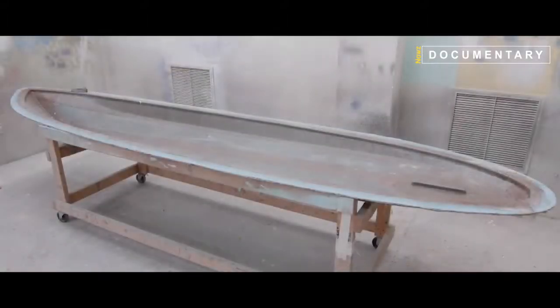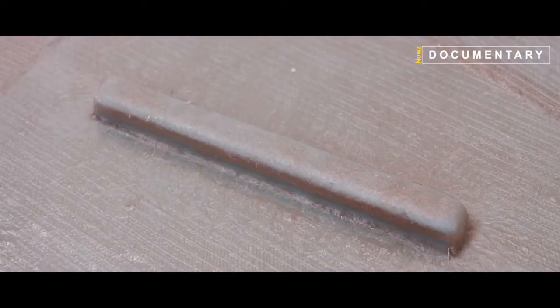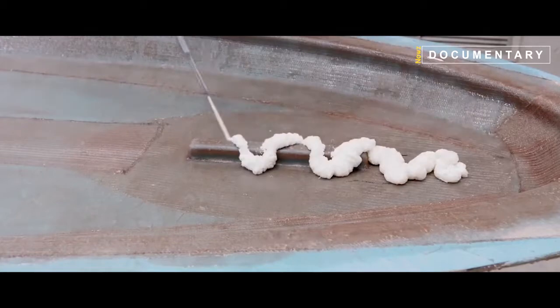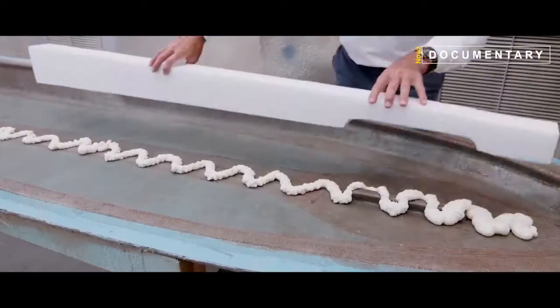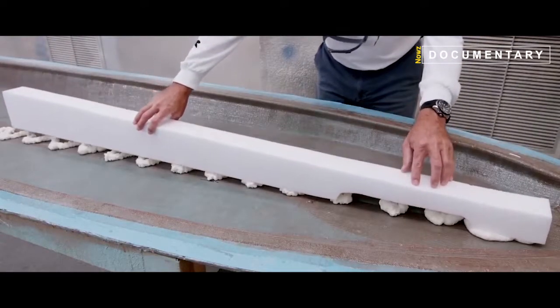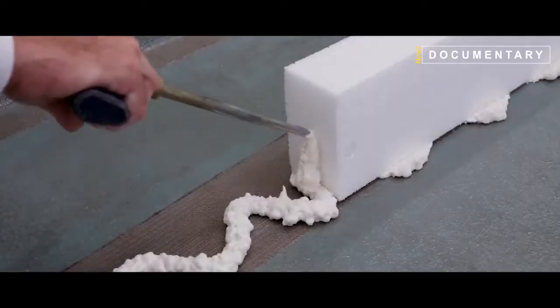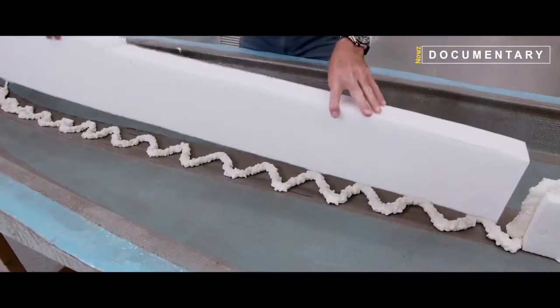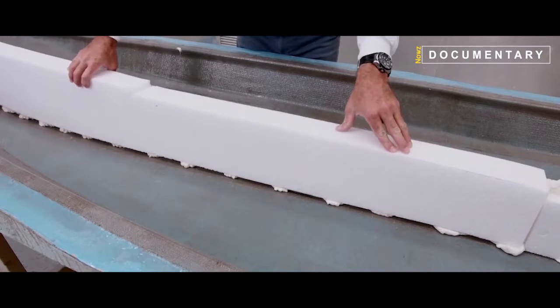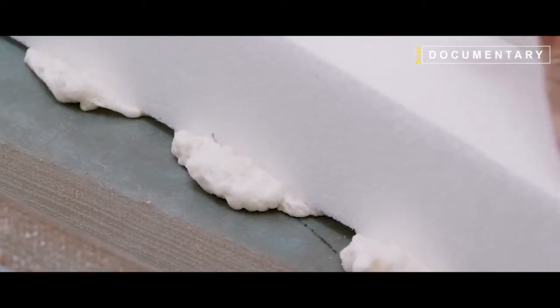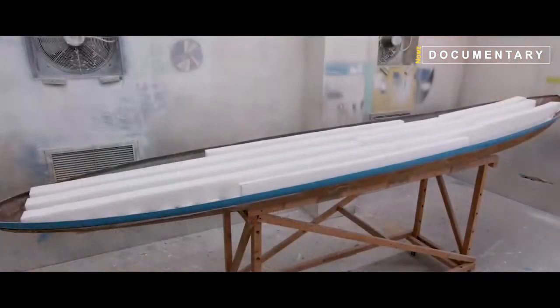The hull's cured vinyl ester resin is now firmly bonded to the structural laminate. The assembler applies expanding adhesive and positions an expanded polypropylene foam stringer inside the hull. The foam stringers are the backbone of the board. They support the weight of the paddler on the deck while keeping the board as light as possible.